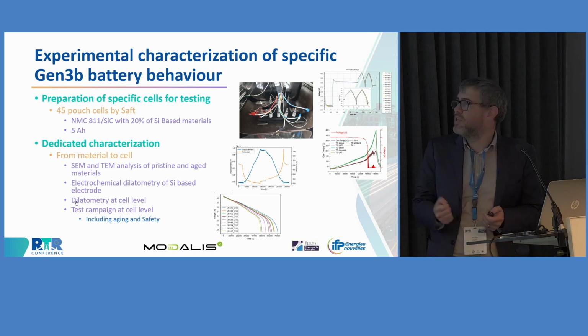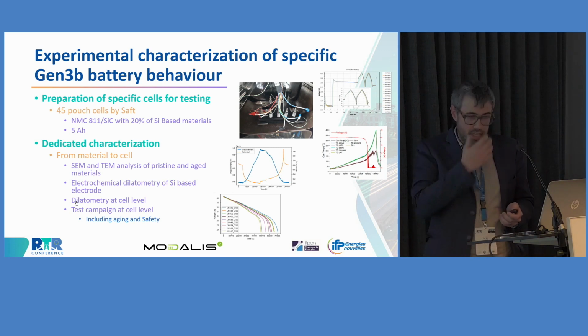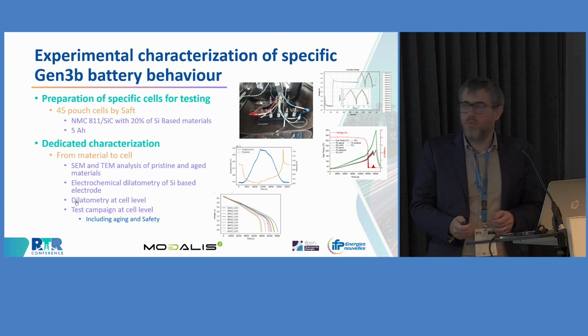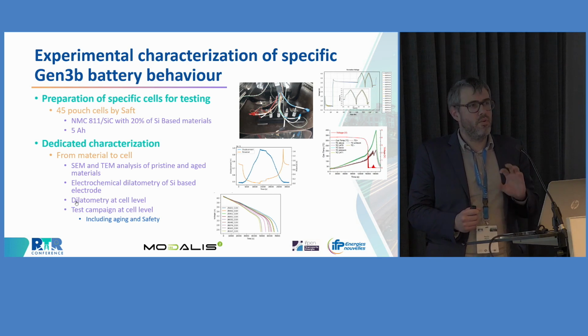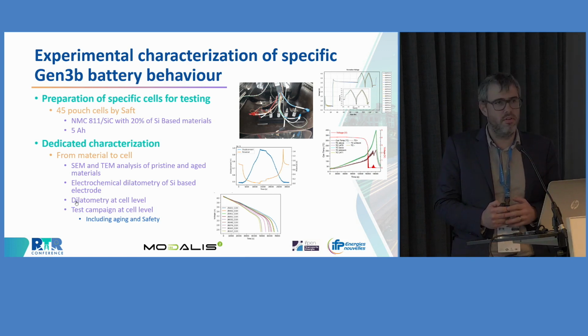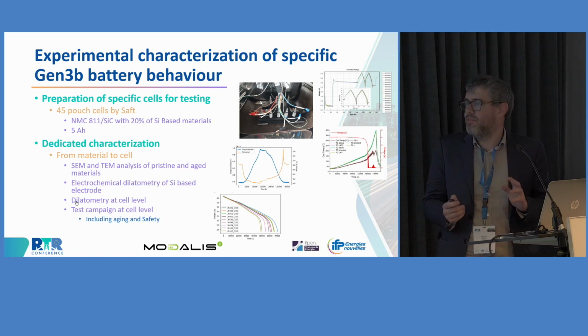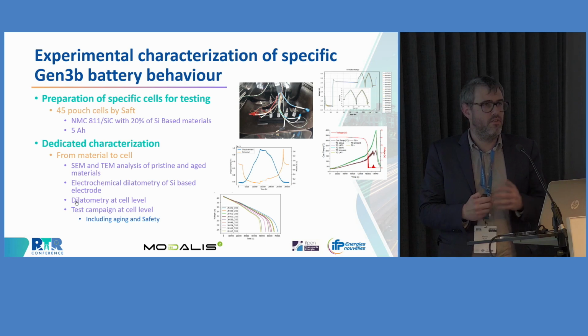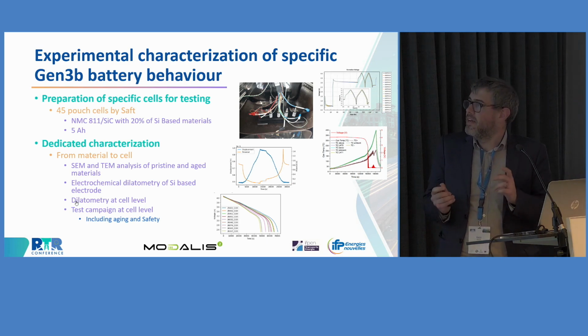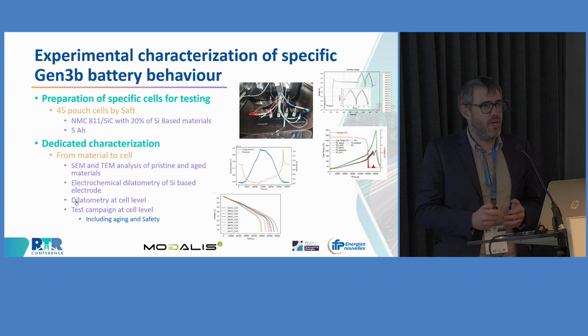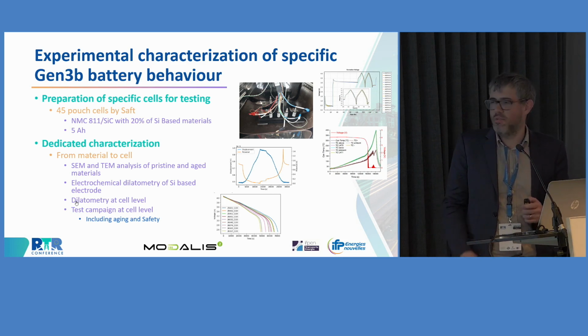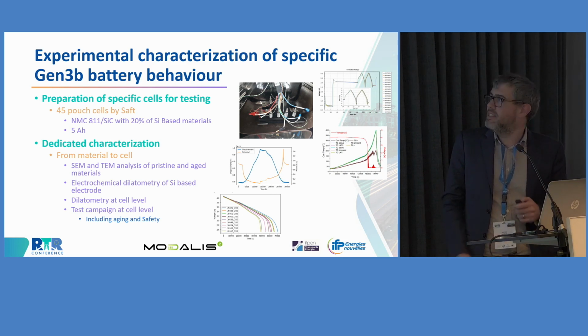So we had to get some material and create the cells. Saft created some cells that were relevant for our project. So it was NMC811 silicon oxide graphite cells. And we wanted to have a huge impact of silicon, so we aimed at 20% of silicon in the negative electrode. So 20% was a way for us to ensure that we had sufficient volumetric expansion at the electrode level and see the impact of mechanical behavior on the electrode. We ended up with 5 ampere-hour cells, so it was less than expected, but due to technical challenges, it was a good result to get these cells and make them work.